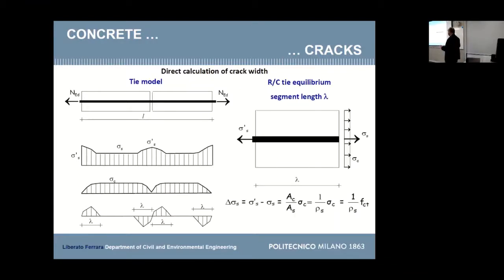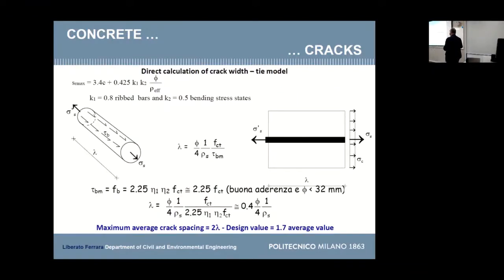Then if you write some other equilibrium and you consider not only the bar, but the wall segment, here is a crack. And here you have the coupled action, concrete plus steel. You find the increment of stress, the stress transfer, which must go from steel to concrete and vice versa. So you combine these equations and we find that the transfer length is proportional to the bar diameter and is inversely proportional to the amount of reinforcement. So the issue is that with reinforcement, you do not avoid cracking. You need pre-stressing to avoid cracking. It's not that if you put more reinforcement, you avoid cracking. No, that is a very bad idea to propose.